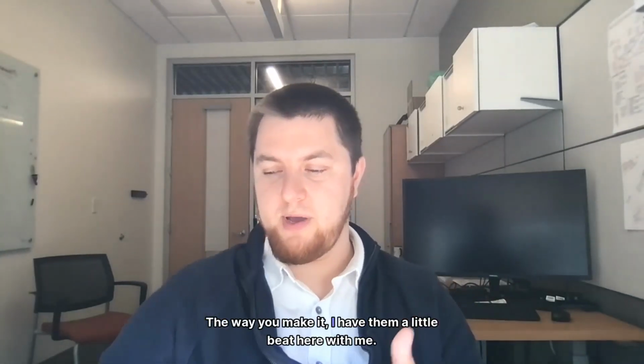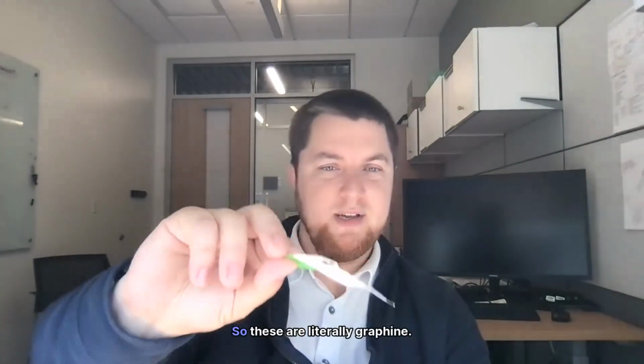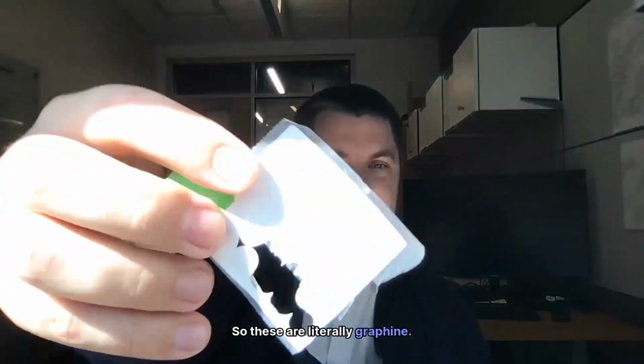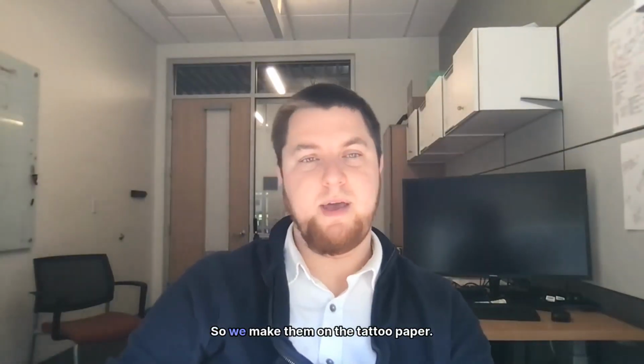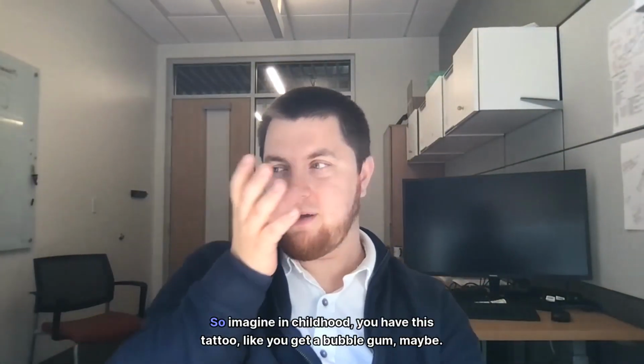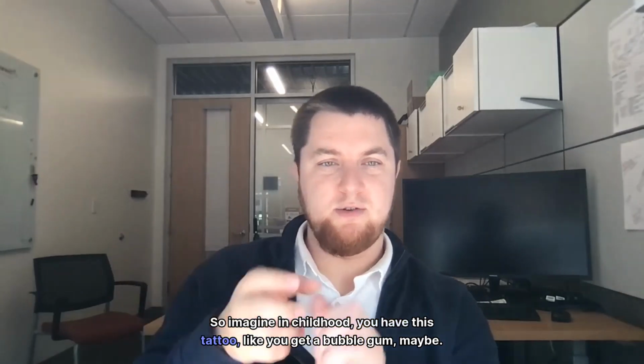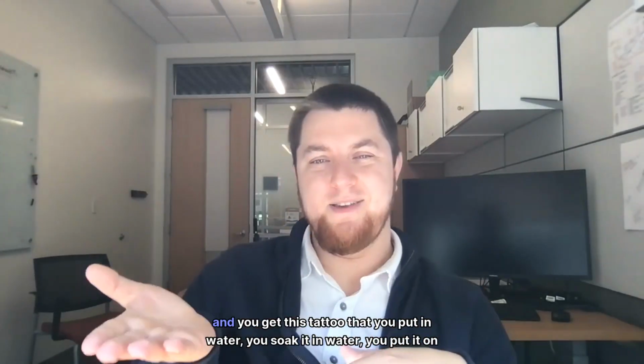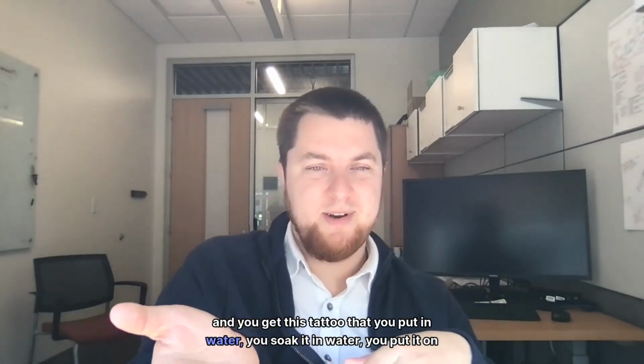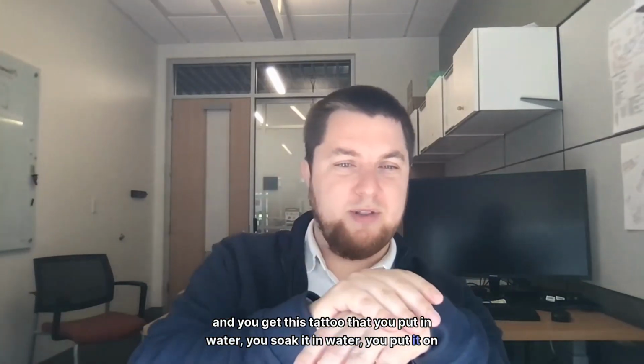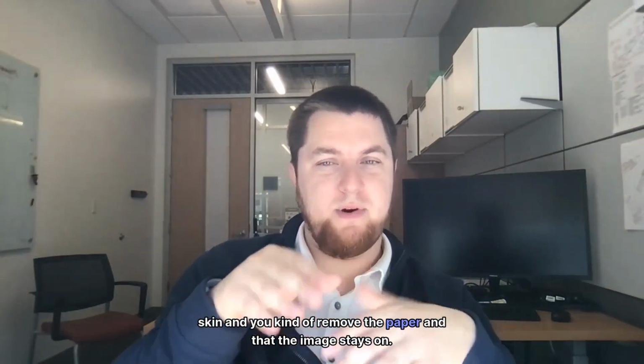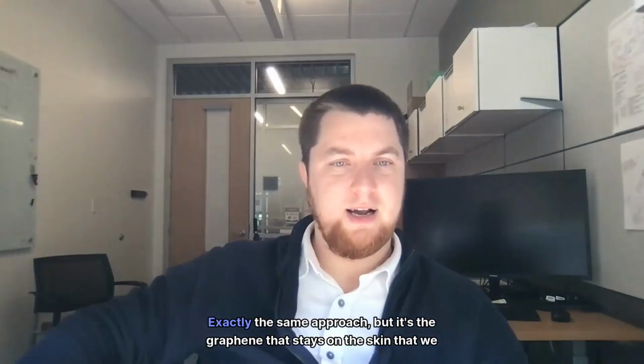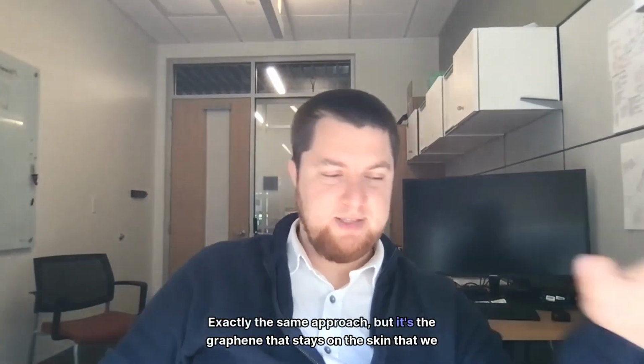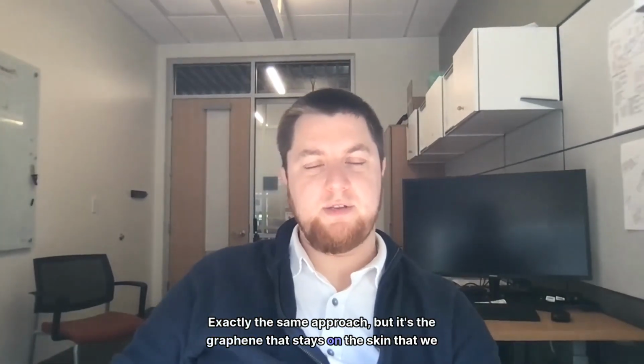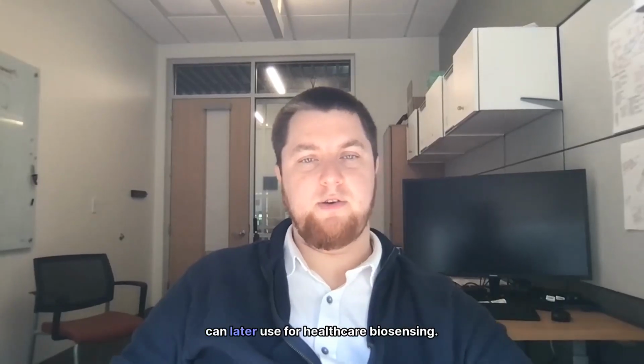The way you make it, I have them a little bit here with me. So these are literally graphene tattoos. I can get a little closer to the camera. So we make them on tattoo paper. Imagine in childhood, you get a bubble gum maybe, and you get this tattoo that you put in water. You soak it in water, you put it on skin, and you remove the paper and the image stays on. Exactly the same approach, but it's the graphene that stays on the skin